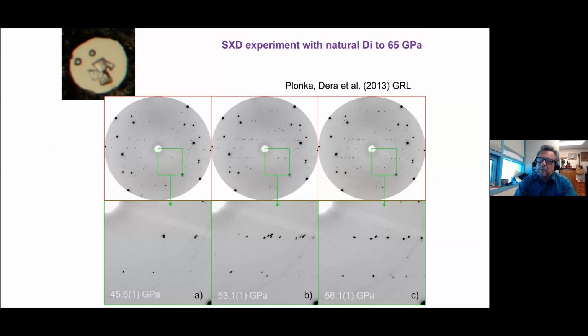And similar methodology, we put several single crystals in a diamond anvil cell, squeeze them at ambient temperature and observe the changes in diffraction pattern and perform crystallographic refinements that reveal how atoms move, how bonds change. So you can see that in this case, at much higher pressure, at about 50 gigapascals, just like before, we observe a change, additional set of peaks appearing.